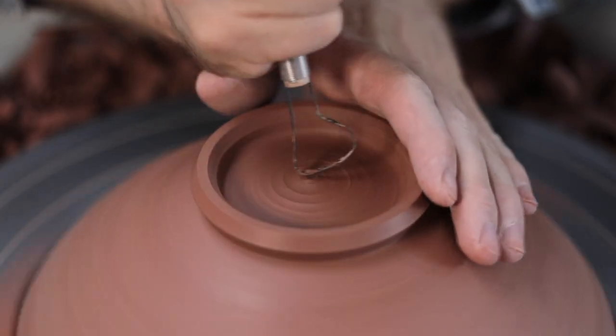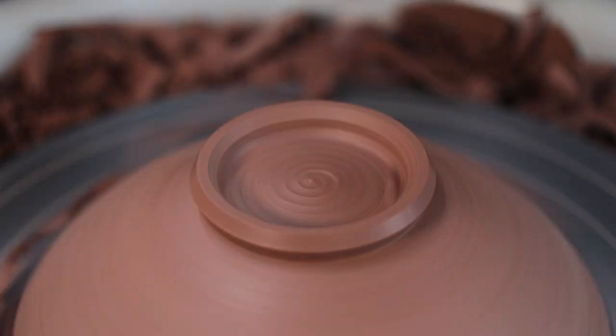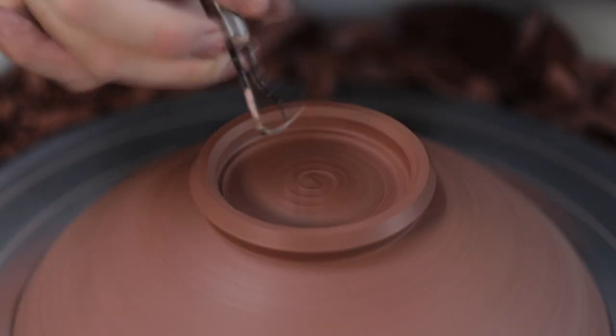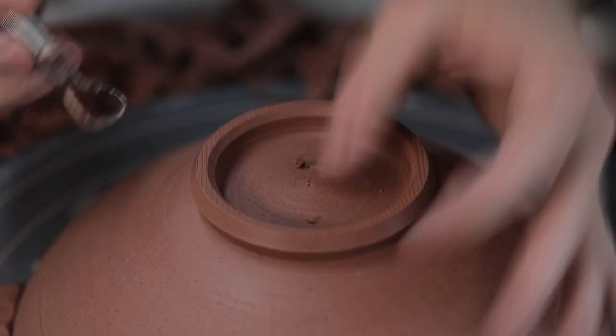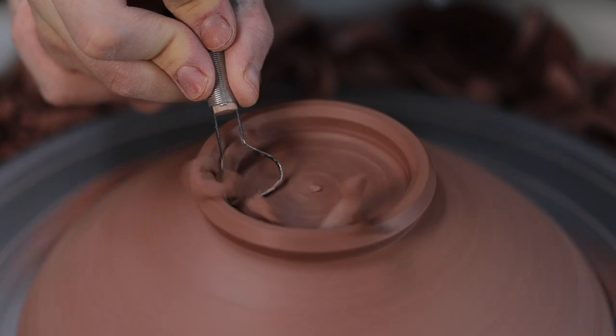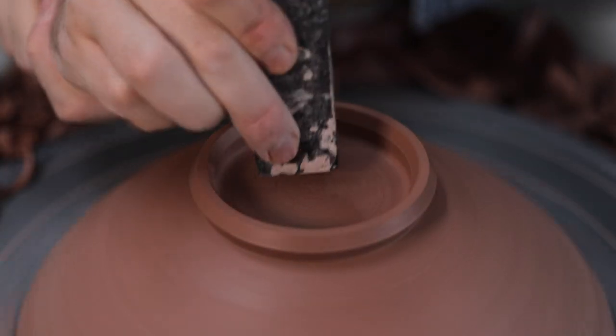You may see potters tapping the undersides of their pots like this occasionally too. A low thud means that it's quite thick, and a higher pitched noise means that it's thinner. Of course the tone changes when you're making different sized pots all the time, but after making hundreds and thousands of these shapes, you can get quite a good idea of what's going on just with a simple tap. And if that fails, I just push on it ever so carefully with my thumb. And if I feel it give, even just a little bit, I know that it's time to stop.